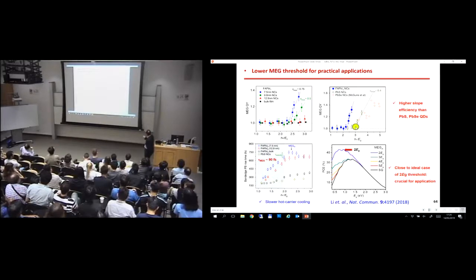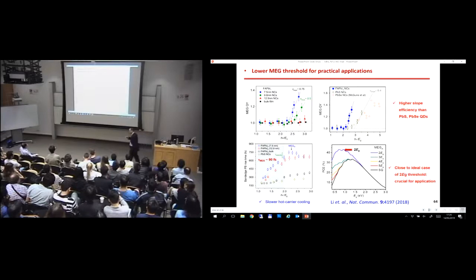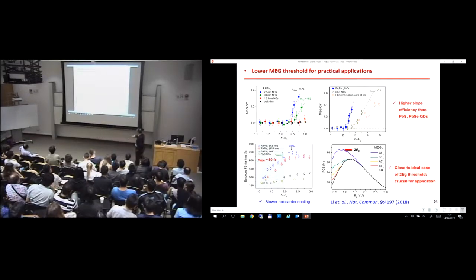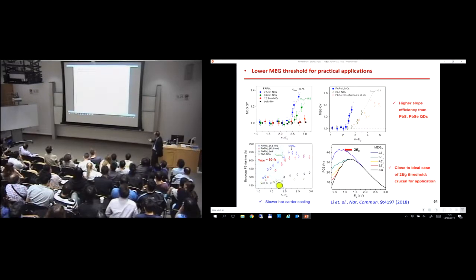Now, the threshold is around 3 times the band gap. If you compare that with the blue dots here, the threshold is around 2.2 EG. So we managed to lower this threshold significantly to close to 2 times with these perovskite quantum dots. Now the MEG lifetimes, we estimated to be around 90 femtoseconds, which is much faster.